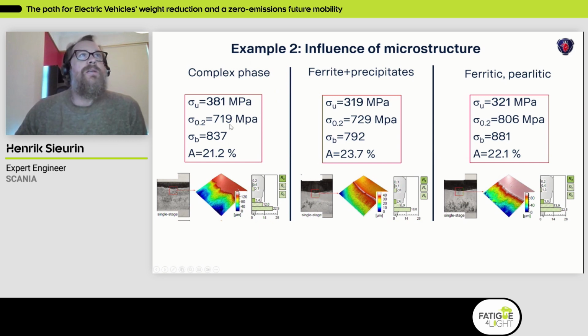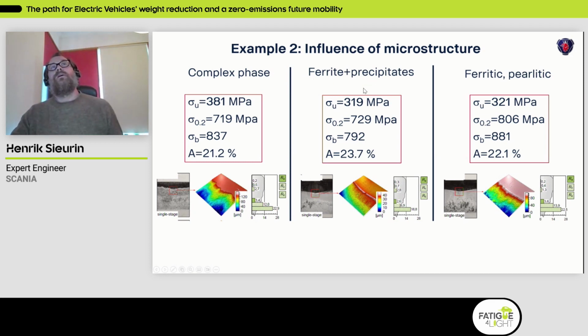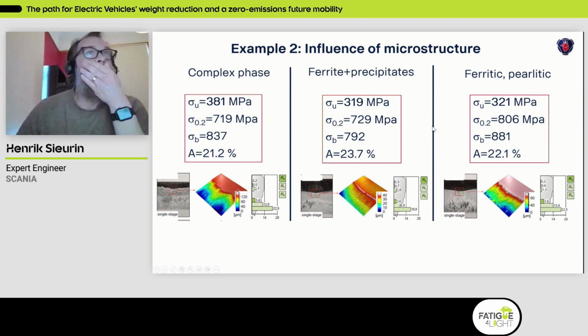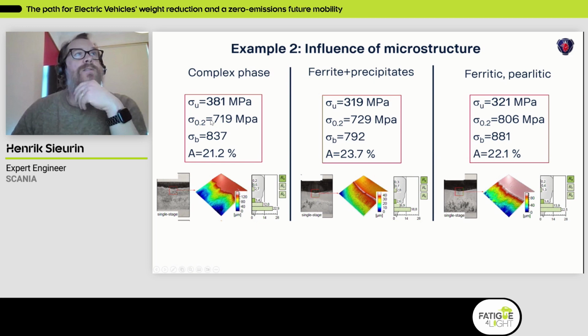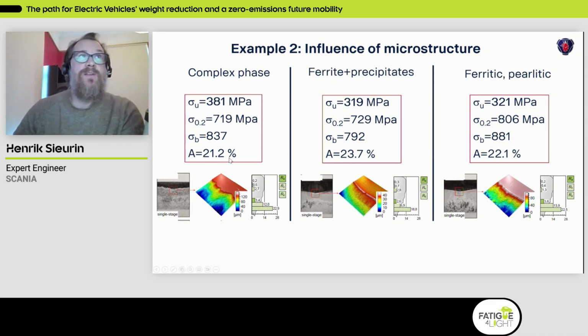We had a complex phase steel, we had a ferritic material with precipitates, and then we have a ferritic perlitic material. And the yield strength was rather similar for these 3 grades. The complex phase had the lowest yield strength. The ductility, elongation was also rather similar. The complex phase actually had the lowest ductility, and the surface roughness was also rather similar. The complex phase actually had the poorest roughness in this fracture zone.